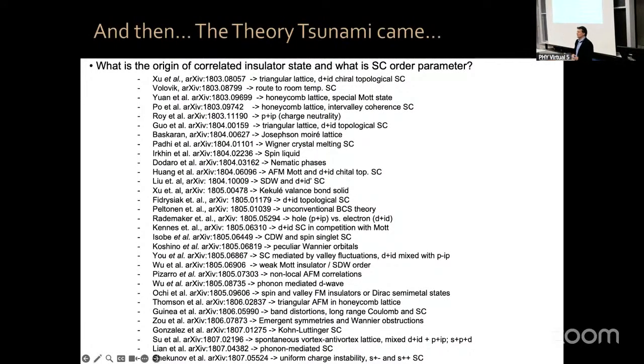Then what happens is, if you have this turbostratic graphite, you're going to have flat bands, remember flat bands were already known, and you're going to have effectively high temperature superconductivity from very strong correlations in these flat bands. So that was in 2013. And then in this paper, which was posted a week or two after we posted our results, he said, finally, someone has done the control experiment. Just take two layers, make a small angle between them, make flat bands, and you see superconductivity. So now, come on, just stack a few more layers and get to room temperature. This is what he told us we should do. Again, I was vaguely aware of those graphite superconductivity experiments. They're very weird, not reproduced and so on. I used to think they were maybe crazy or whatever. Now I'm like, who knows?